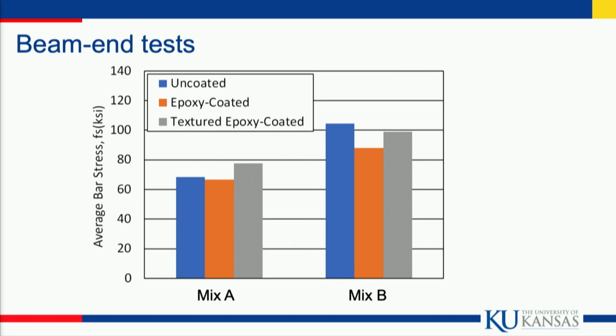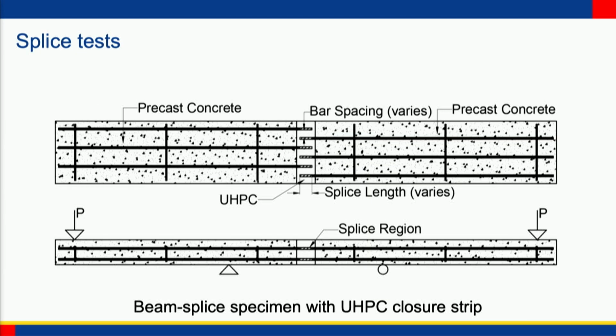We looked at both mix A and mix B. We looked at all 3 types of bar surfaces. Notice that in all cases, the uncoated and texture-coated bars were stronger than the epoxy-coated bars, which is the orange in the middle, but that the texture-coated bars, in one case, gave higher strength than the uncoated bars, and in other cases, a little lower. But this is what we're seeing. And so between mix A and mix B, mix B had the better fiber distribution, so we stayed with that for the next series of tests. Here are splice tests.